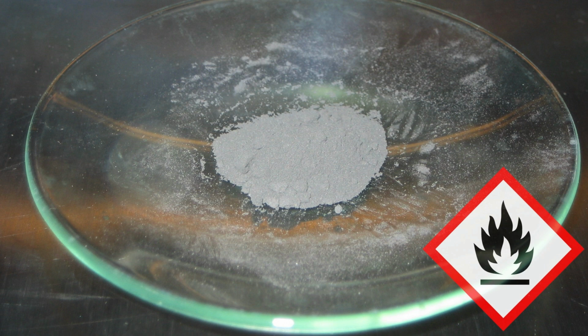Section 4. Safety. Due to its large surface area and high volume of contained hydrogen gas, dry activated Raney nickel is a pyrophoric material that should be handled under an inert atmosphere. Raney nickel is typically supplied as a 50% slurry in water. Care should be taken never to expose Raney nickel to air. Even after reaction, Raney nickel contains significant amounts of hydrogen gas and will ignite when exposed to air.